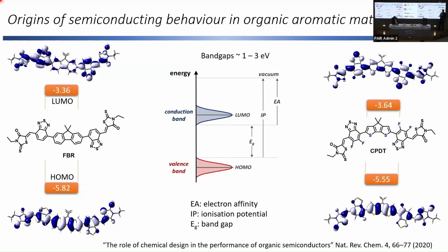These days, I think the common problems that they used to have with the stability of the thiophenes are no longer really an issue. And if you really look to long-term stability, look at an OLED. An OLED has 3 organic species, red, green, and blue. And these materials have been in the marketplace for 10 years now. If you buy an OLED television, you're going to want it to last 15 years minimum. So in principle, if you make them pure, if you use kinetics, in other words, thinking about barriers, and then tweak the energy levels, you should be okay. So it's not as much a concern as it used to be.